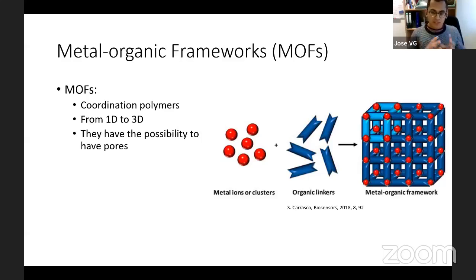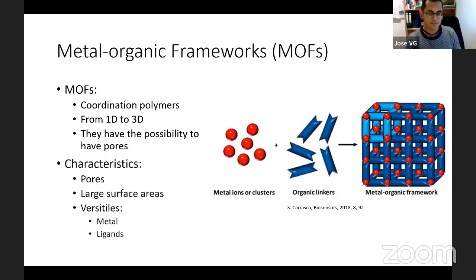The directionality that the ions give to the ligands will make this material crystalline. So it's possible to study by crystallographic techniques. And if we use photocrystallography, we can try to track the structural changes after light irradiation. These materials are interesting because of the pores, because of the large surface area they have, and because they are very versatile. You can change the metal and the ligands in many different ways.